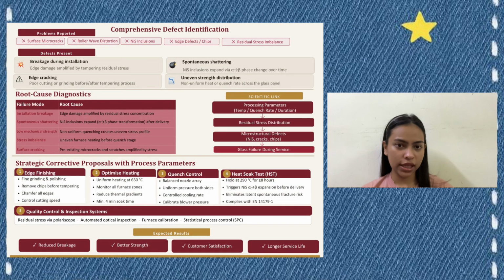So how do we fix it? We implement 5 strategic corrective proposals. First is edge finishing, fine grinding and chamfering edge before heating to eliminate those microcracks. Second, optimize heating, keeping the furnace at a strict 650 Celsius with at least a 4-minute soak time.